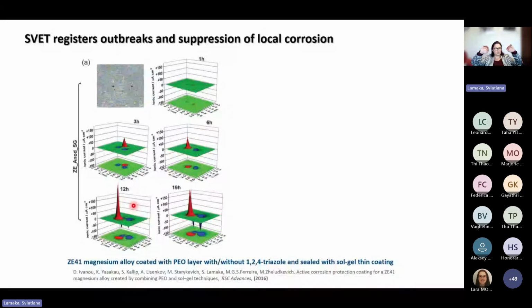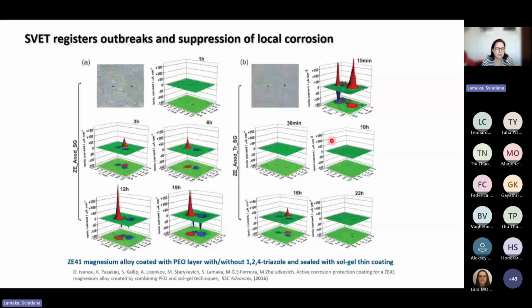For example, if you work with coated samples, some cathodic activity might be undergoing under the coating, and then you're not able to visualize it properly with SVET. Or typically cathodic areas are larger, and hence total activity per surface area is somewhat lower, and SVET might also miss this. So in reality, we sometimes see that this condition is not always true, but we typically should be able to find out the reasons for this. And this is an example where we compared integrated anodic and cathodic currents. Again, this is ZE41 magnesium alloy with a number of inhibitors loaded in various carriers, and here we clearly see initial strong corrosion activity in one of these samples.